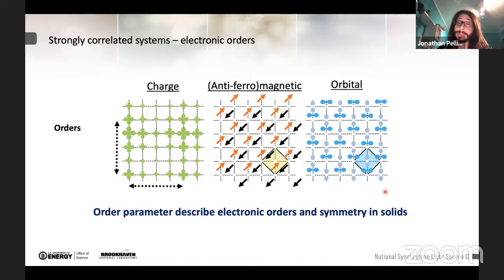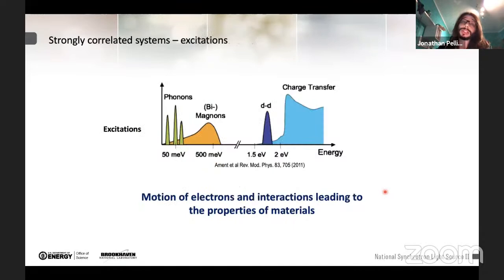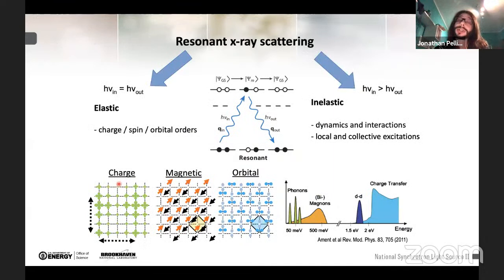But besides the static properties, it is important to understand what the elementary excitations and the electron dynamics in these materials are. And here I want to present all of the different excitations that are important to know if we want to understand and explain the interactions present inside materials. On the order of eV, we have charge transfer and dd excitations. And then as we decrease the energy, we have magnons and spin excitations. As we decrease the energy more, we have phonon excitations. And nowadays we can also add even lower energy amplitude and phase modes. And on this aspect, resonant X-ray scattering is a pretty powerful technique because it can be used to investigate both of these aspects in quantum materials.